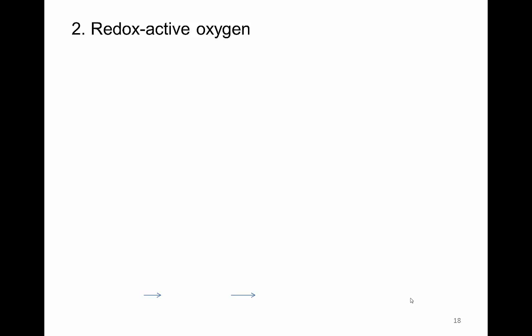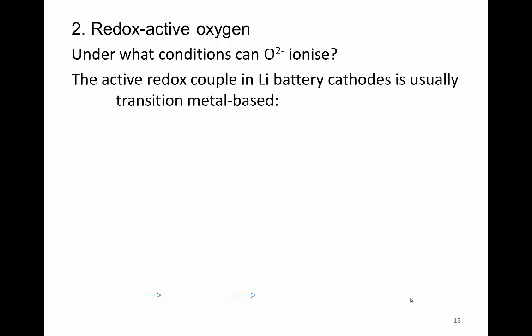Second area, which has become of interest in the last 2 or 3 years and has suddenly become a hot topic in lithium battery materials development, and that concerns the oxygen in the oxides in the cathode. Because we normally think that oxygens are present as O2 minus ions, and any chemist will tell you, yeah, oxygen is O2 minus. But the question is, is it always O2 minus, or is it possible that the oxide ions can ionize? Can they liberate electrons to give, for example, O minus ions? Interesting question. And there is now evidence, a lot of good evidence, that this can happen under certain circumstances.